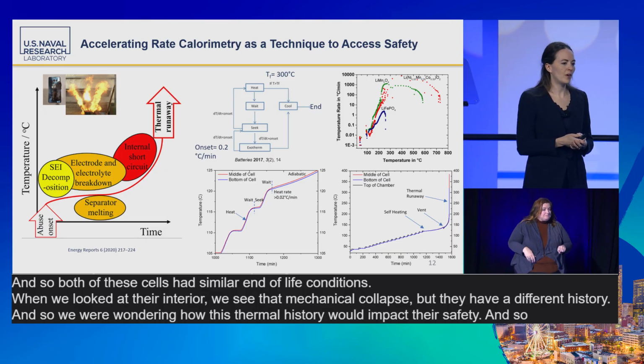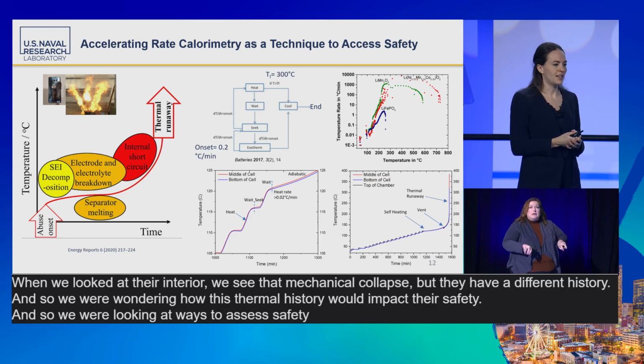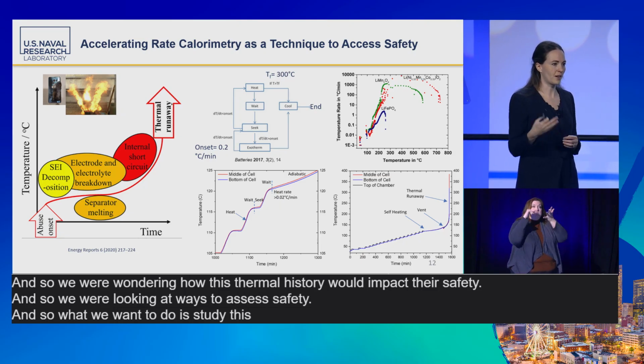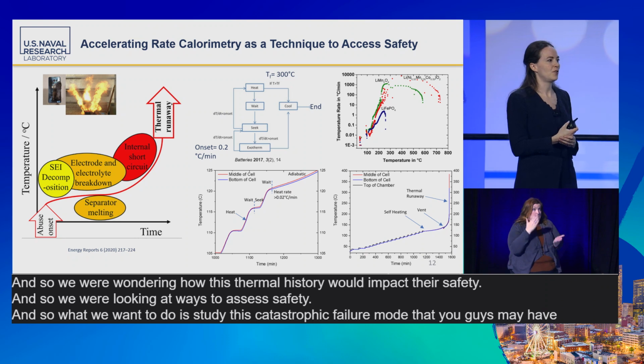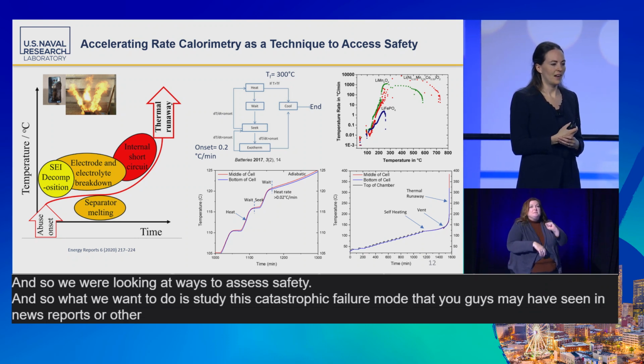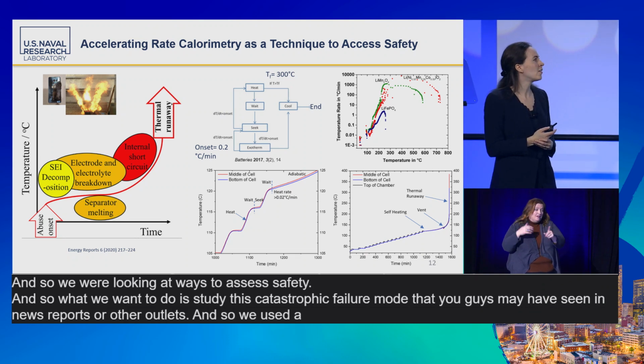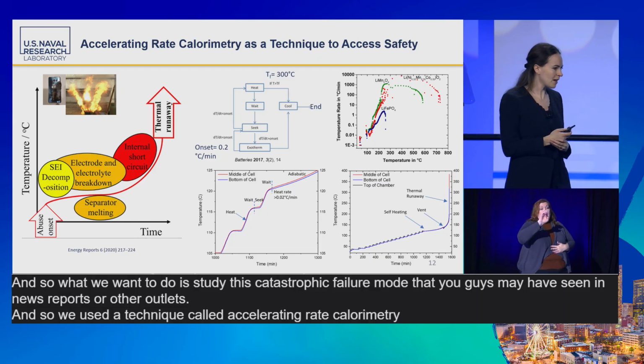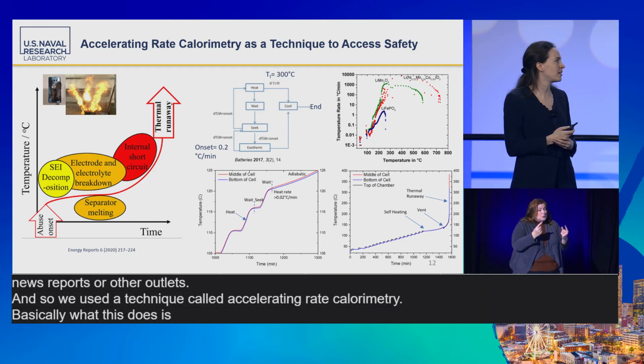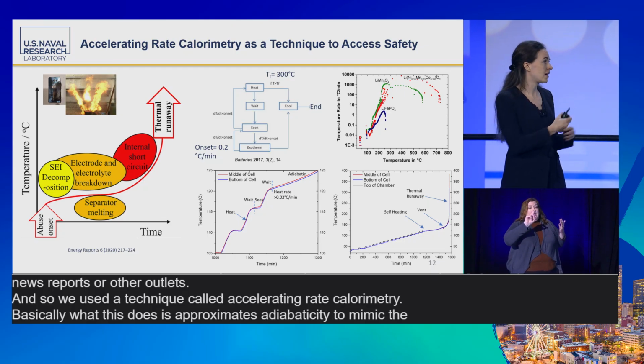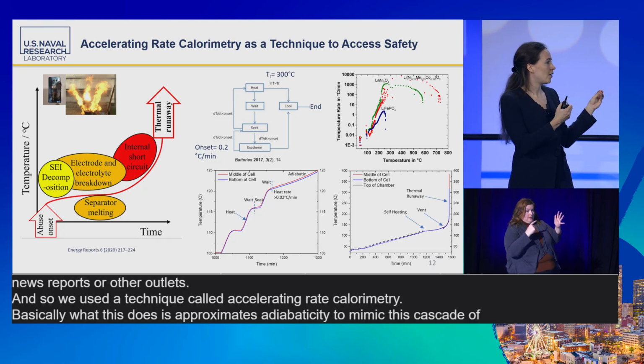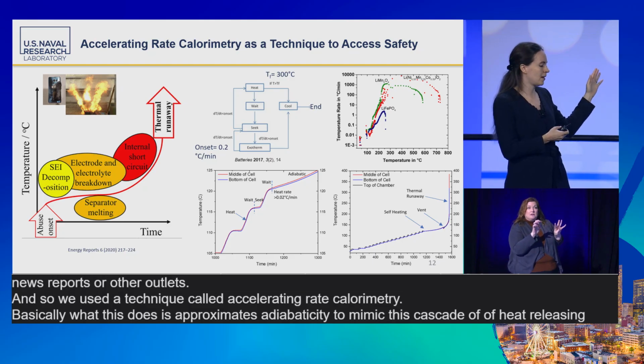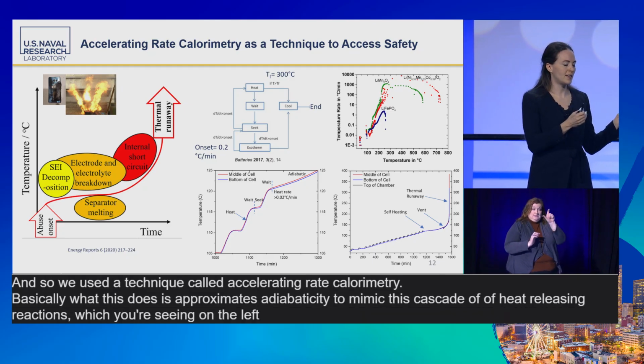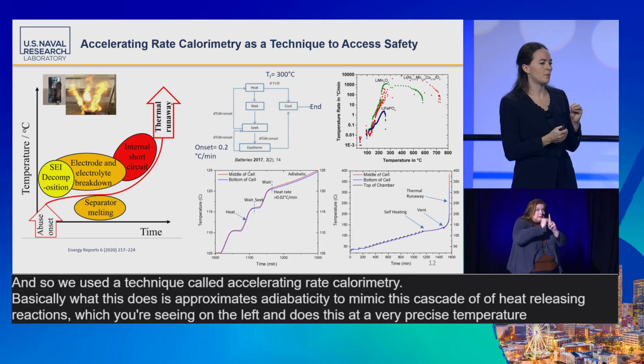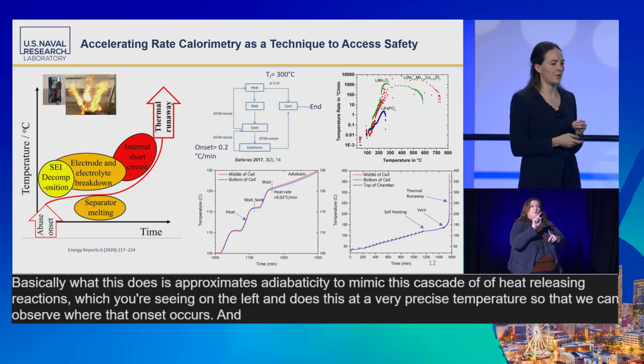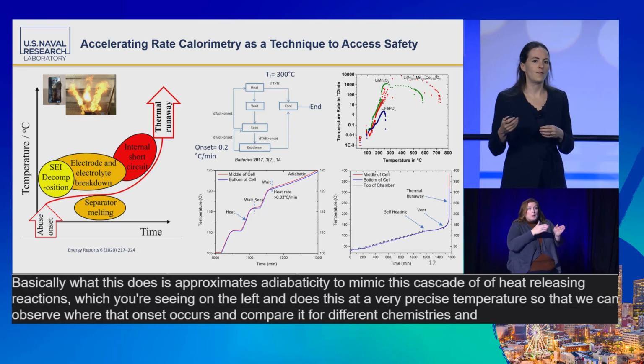And so we were looking at ways to assess safety. What we want to do is study this catastrophic failure mode that you may have seen in news reports or other outlets. And so we used a technique called accelerating rate calorimetry. Basically what this does is approximate adiabaticity to mimic this cascade of heat-releasing reactions, which you're seeing on the left, and does this at a very precise temperature so that we can observe where that onset occurs and compare it for different chemistries and other factors of the battery.